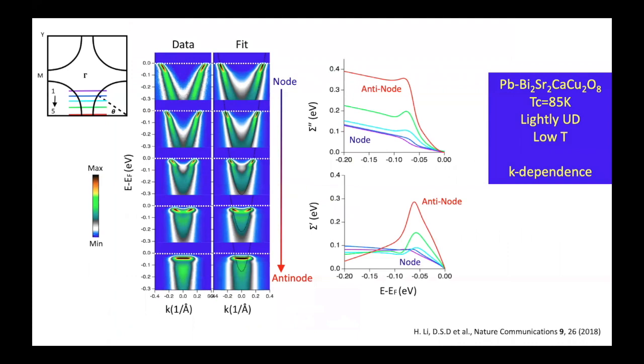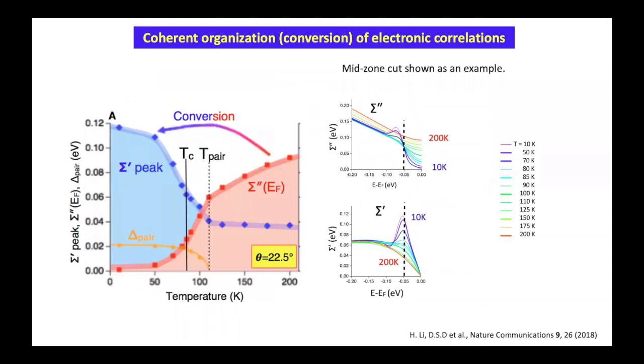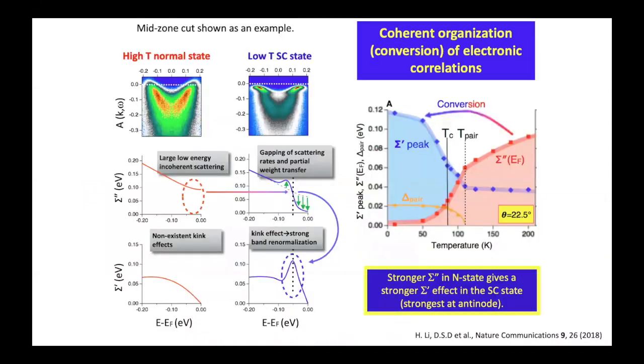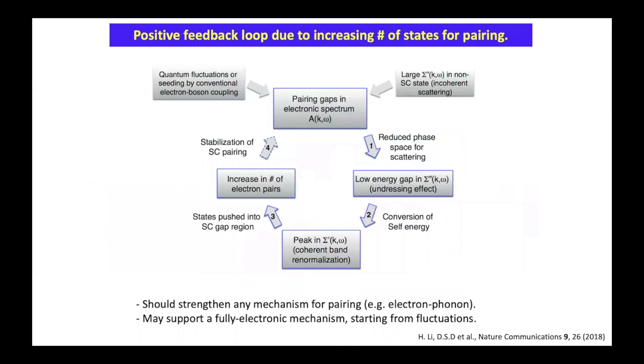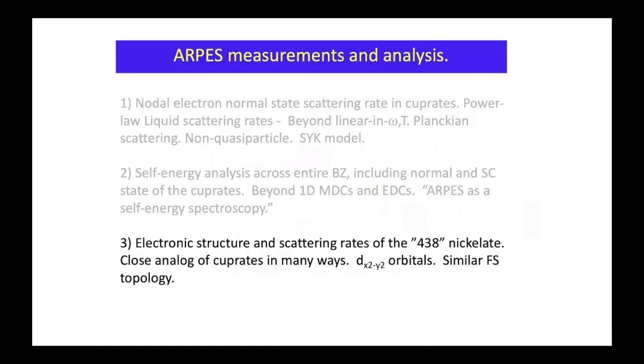Here's 300 some millivolts at 50 some millivolts. So that's huge sigma double prime compared to energy, extremely non-quasi-particle-like. Along with that is a huge effect on sigma prime. This gives these kinks and whatnot, and extremely flat bands. So my time is a little tight. What we observe is that as a function of temperature, there's a conversion of this huge sigma double prime to a sigma prime, from an incoherent thing to a coherent thing. That starts slightly above Tc at about a pairing temperature, some 20 Kelvin above. And there's details of this. We believe it gives positive feedback onto the pairing that can help strengthen pairing mechanisms, but more work needs to be done on this.